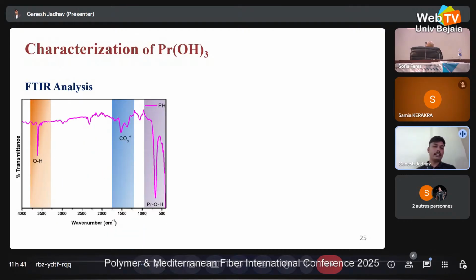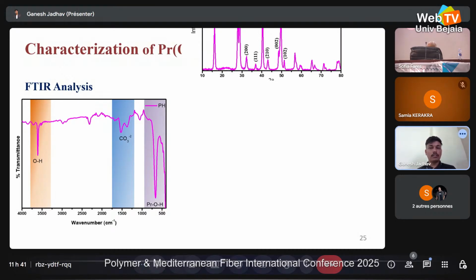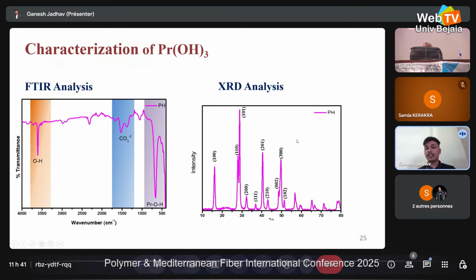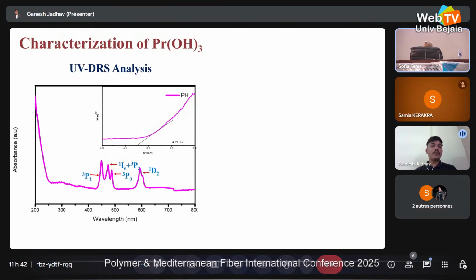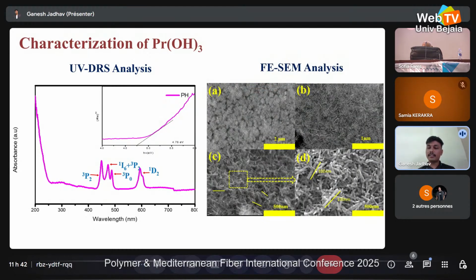So after complete synthesis, we move forward to characterization. In characterization, we did its FTIR analysis, and the prominent peak at 550 shows the confirmation of the Pr(OH)3 compound, and in XRD we matched this XRD with JCPDS, and we come to know that it is Pr hydroxide. Then we go towards the UV DRS analysis, and also we did SEM analysis. In SEM, we can clearly see the nanorod like structure.